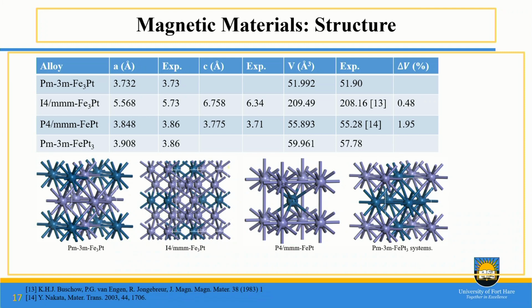So we have done some calculations on these structures or these alloys. The first work that we have done was on the FePt alloys. We have done various compositions according to how they occur in nature. And with the calculations that we have done, if you look at the percentage difference of the experimental volume as well as the calculated volume, you see that there's not much difference. It means that our calculations were able to reproduce what has been found experimentally.